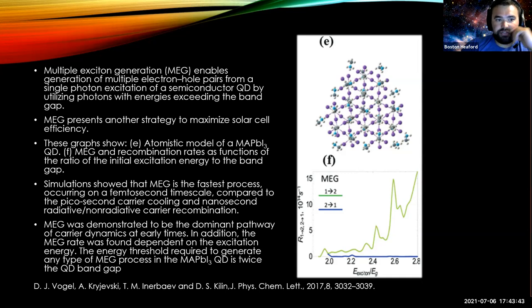These graphs show an atomistic model of the methyl ammonium perovskite quantum dot, and then multiple exciton generation and recombination rates as functions of the ratio of the initial excitation energy to the band gap. The simulation showed that multiple exciton generation is the fastest process, occurring on a femtosecond timescale compared to the picosecond carrier cooling and nanosecond radiative and non-radiative carrier recombination.